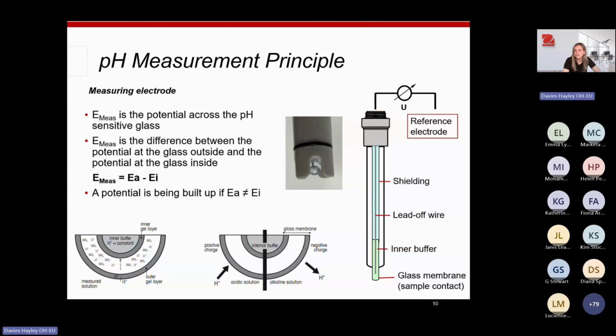The measuring electrode: inside, you have the lead-off wire, which is immersed in the inner buffer. This lead-off wire carries the electrical signal, or the voltage, to the meter. You've got the glass membrane, or the tip. We'll call it the glass membrane, the tip, either or really. The tip is made of specialized pH sensitive glass. When it's dipped in a liquid, a thin hydrated gel layer forms on the outside, and hydrogen ions in your sample react with this layer, creating the voltage essentially that the meter reads.